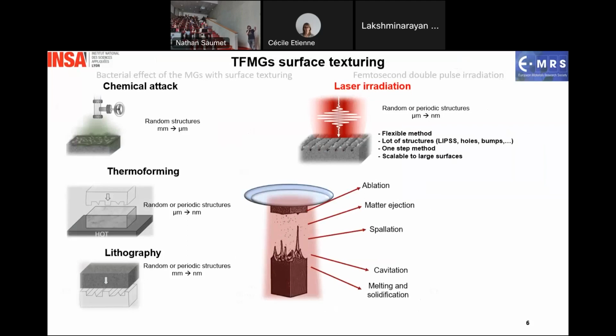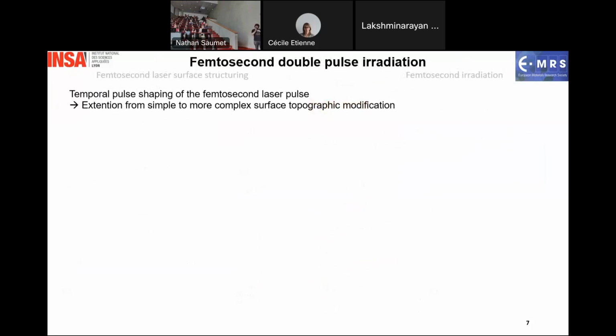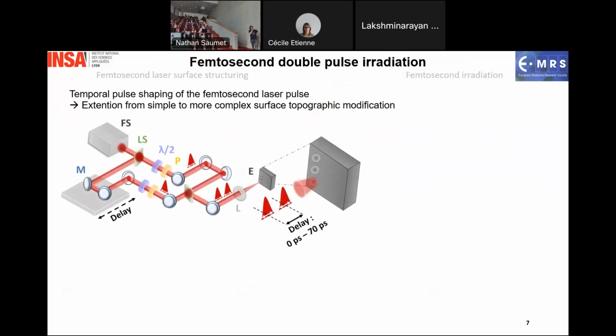We have all the physical interactions between an ultrashort laser pulse and the surface, with cavitation, spallation, ablation, etc. What is important here is that we have a texturing with topographic and chemical changes of the surfaces. To increase the possibilities of surface texturing, we also worked on temporal pulse shaping with double pulses, which permits much more complex geometries. The setup is shown here with a Mach-Zehnder interferometer with a delay line. By moving this delay line, we can choose the delay between the pulses from 0 to 70 picoseconds.